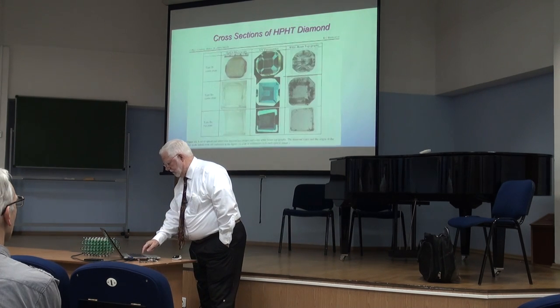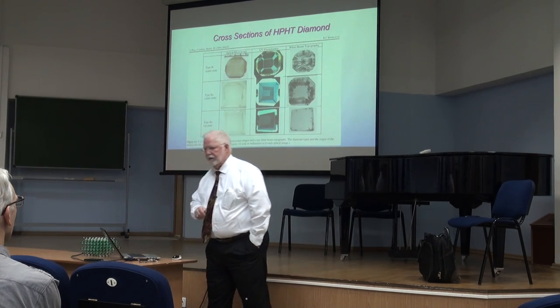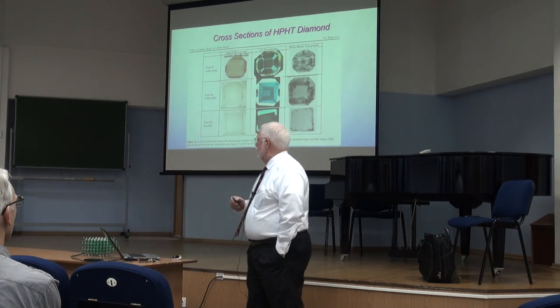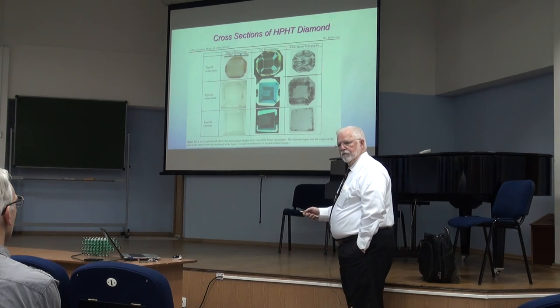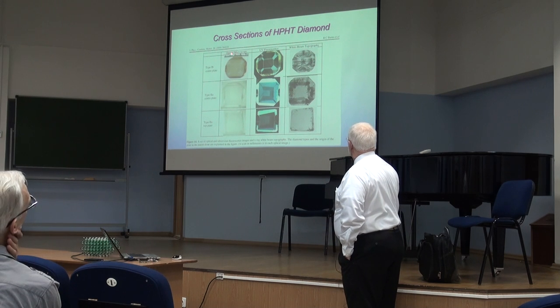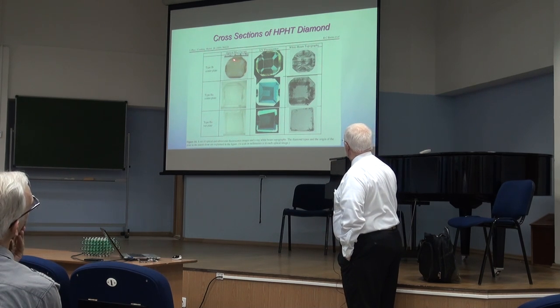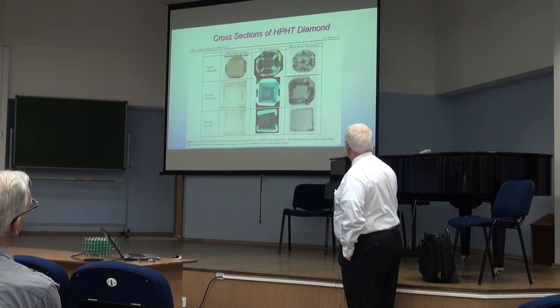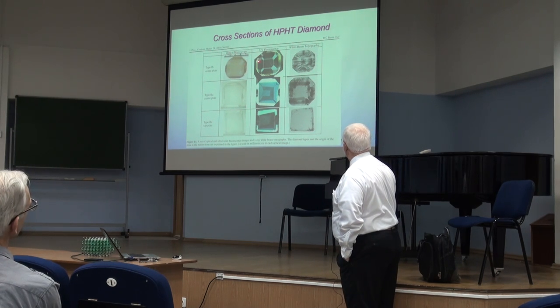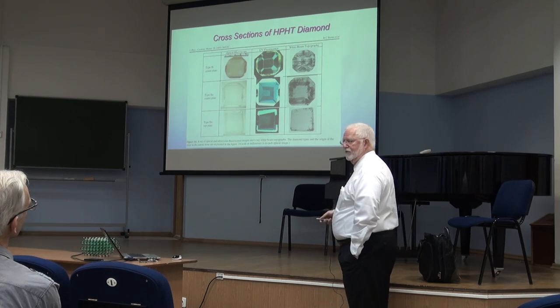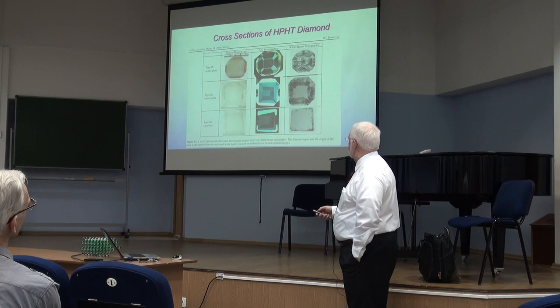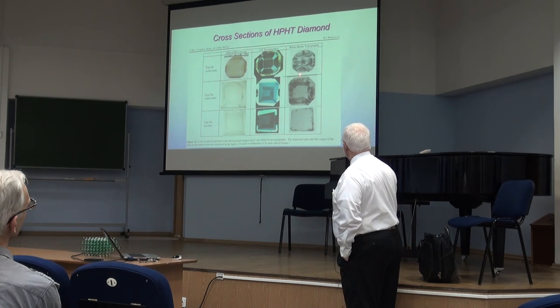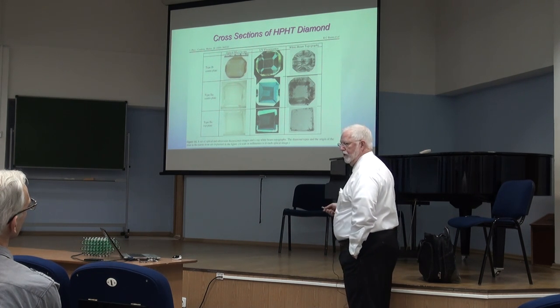But natural diamonds, HPHT diamonds, like natural diamonds, also have growth structure inside them. Here you can see a higher nitrogen yellow concentration in this growth sector versus these growth sectors. That shows up in the UV fluorescence in different ways. And this is an X-ray technique that looks at extended defects or dislocations in the material. And again, you can see each of these has a particular structure or pattern.